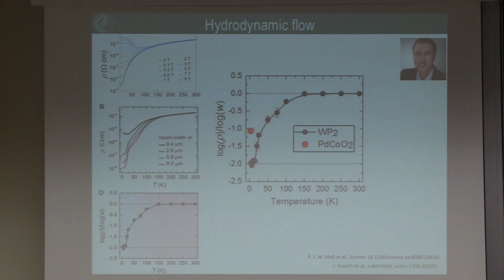So simply to remind you, it's really interesting. You have this magnetic field dependence, you have the width dependence, and this looks really like a hydrodynamic dependence. So I asked Johannes, we should find out - something similar must go on here, we should get the same behavior. It looks like we get the same behavior in a magnetic field as we get when we make this material width dependent. This is simply for comparison, palladium cobalt O2.